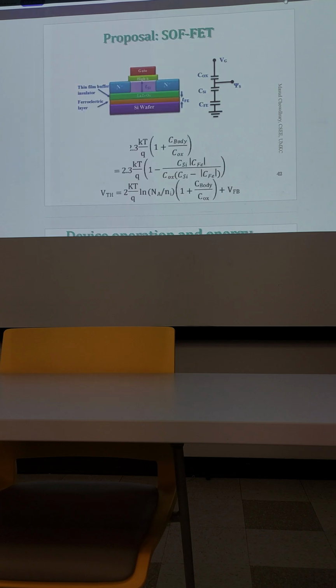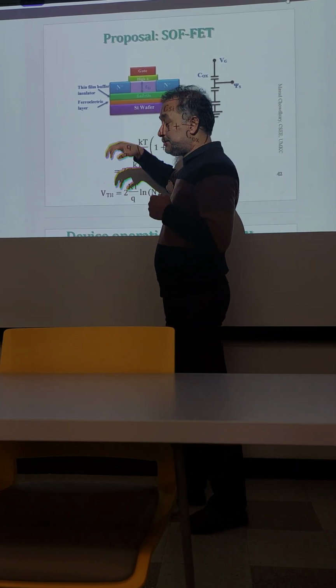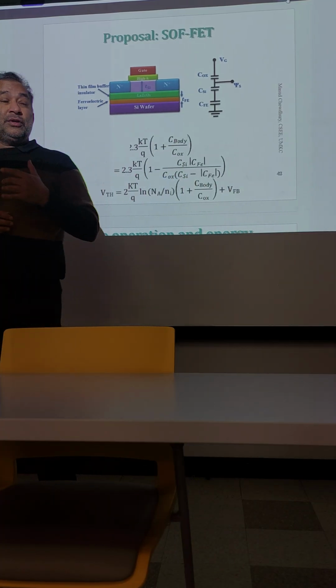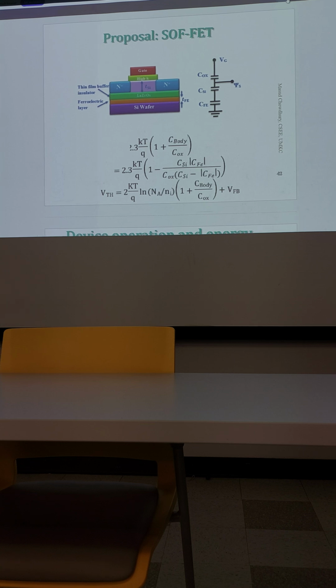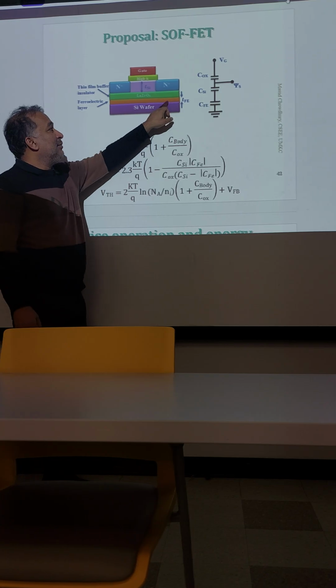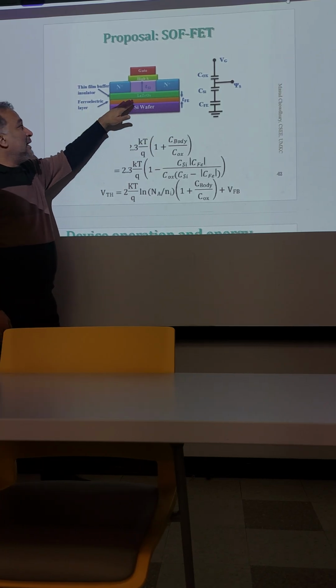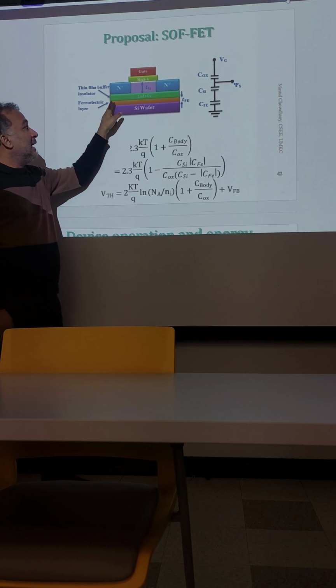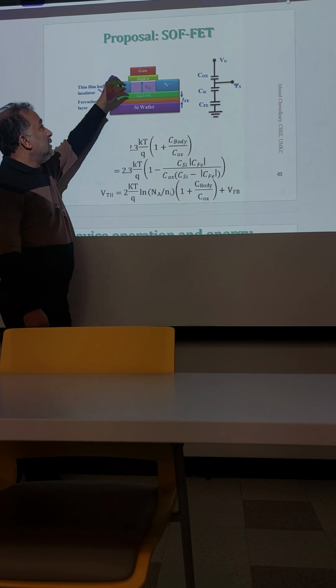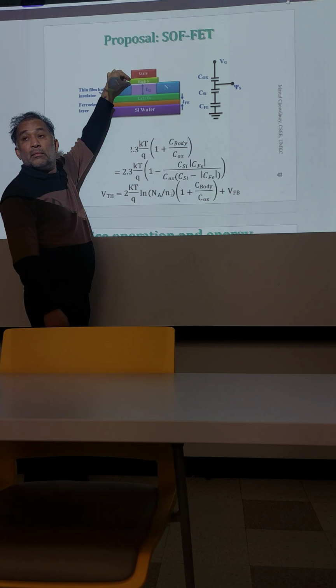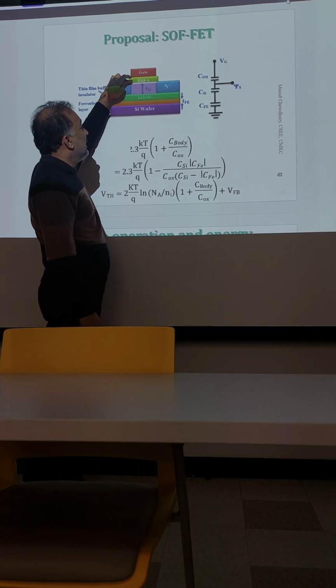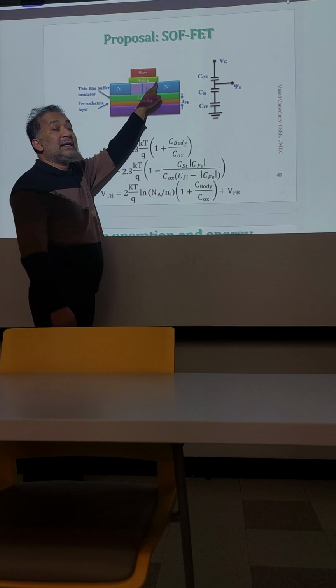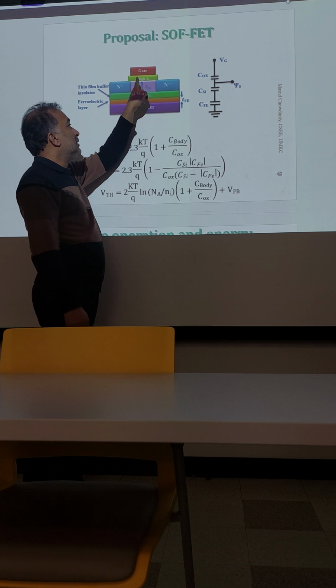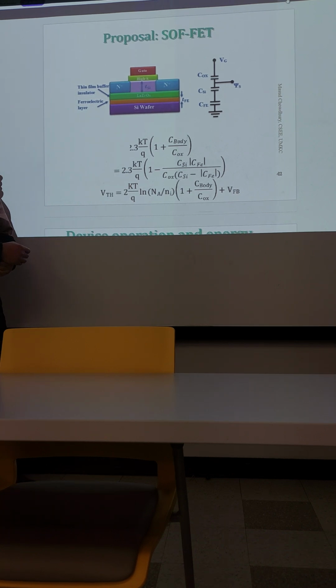So the question now is, how do we achieve this? As I mentioned, we have to insert a layer of ferroelectric insulator. But the challenge that the original inventor group, Salahuddin and his group, faced is that ferroelectric materials are very active. When it touches silicon, it reacts with silicon and forms a silicate layer. So if I put the ferroelectric insulator here, the bottom surface of that insulation layer will react with this silicon channel and form a silicate layer, changing the property and structure of the channel and the gate both.